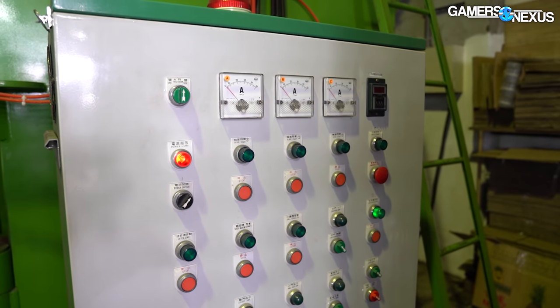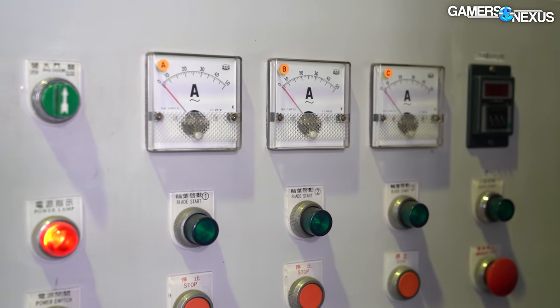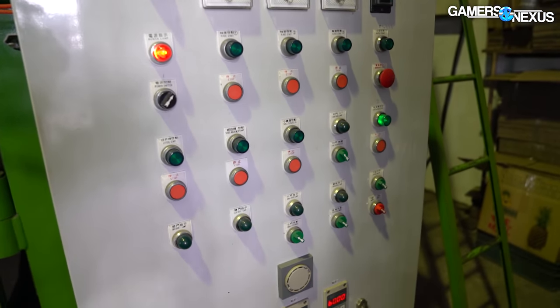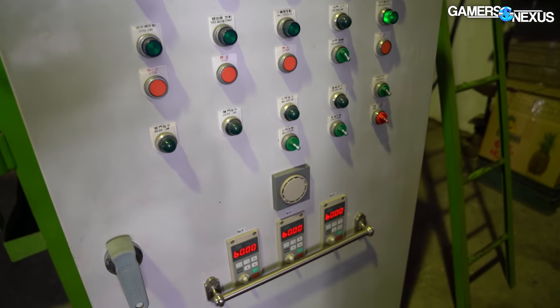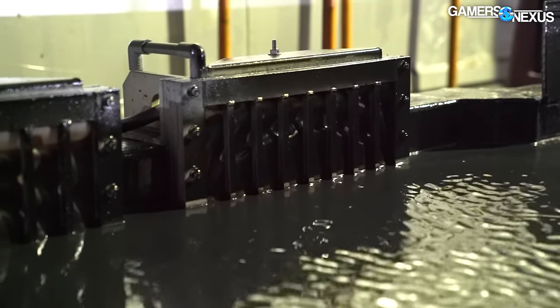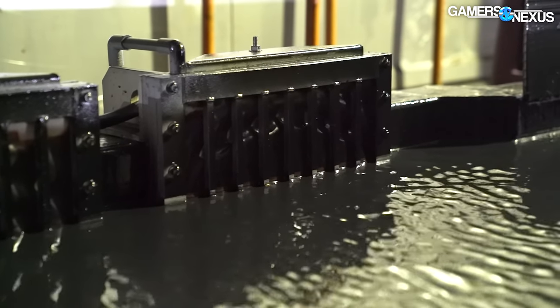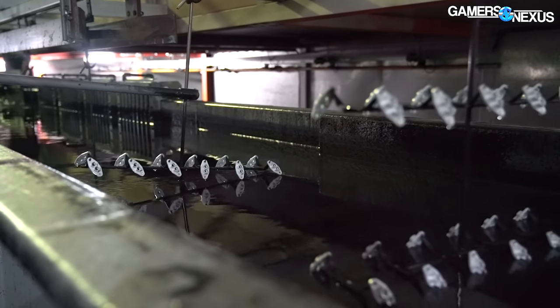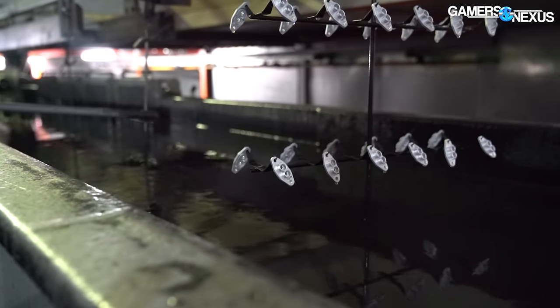The painting tubes are hooked up to a large green box that's effectively a pump, with a dual-chamber reservoir of paint and water connected via hoses. The pump and the cooling solution need to be kept at 26 to 28 degrees Celsius to prevent coagulation within the tubing. The tank uses radiator-looking anode diaphragms on each end, which help even out the distribution of electricity through the tank and through the product. As the product is dipped into the coating, it sparkles from the current passed through it. On the way out of the paint tank, the product is sprayed with a misting of water to help stabilize the paint.